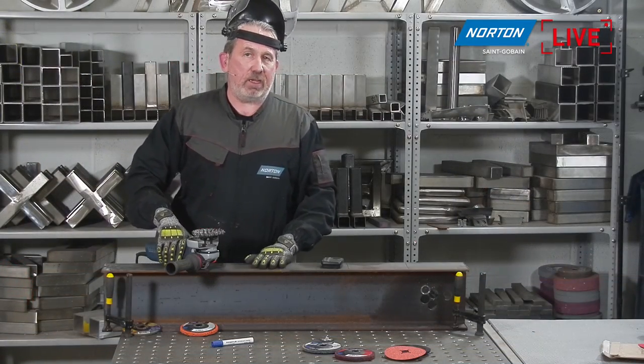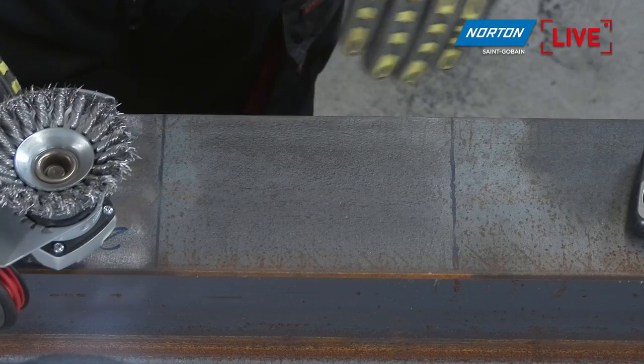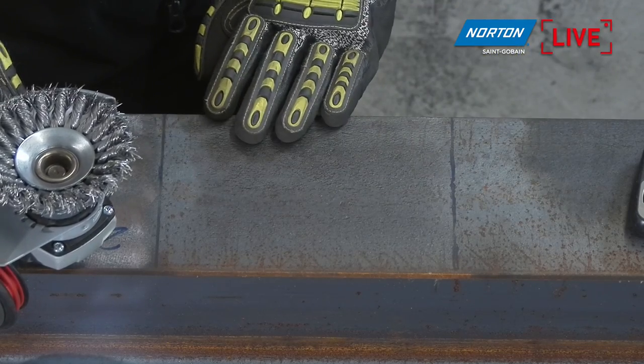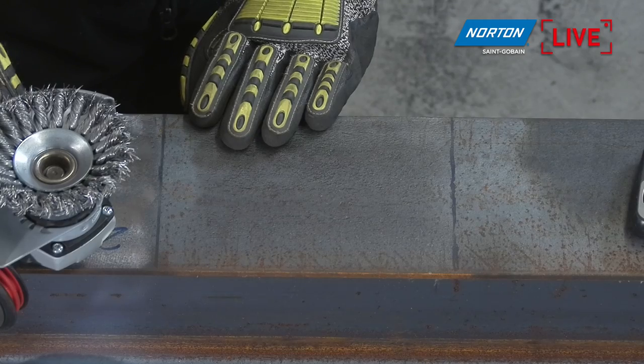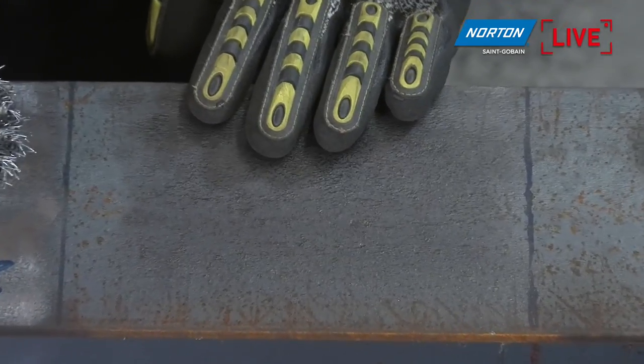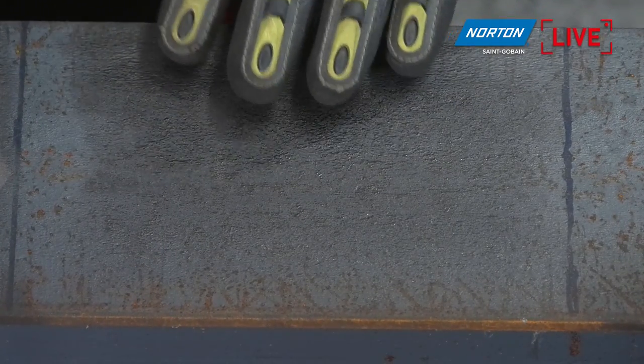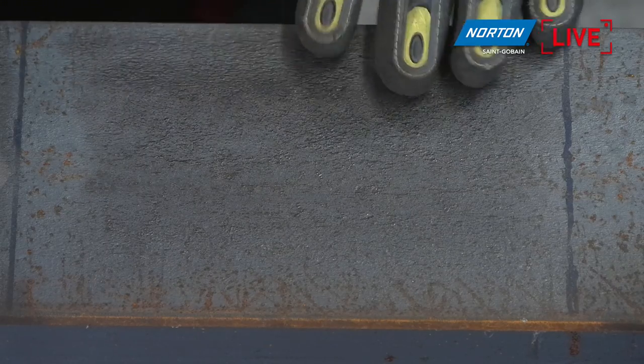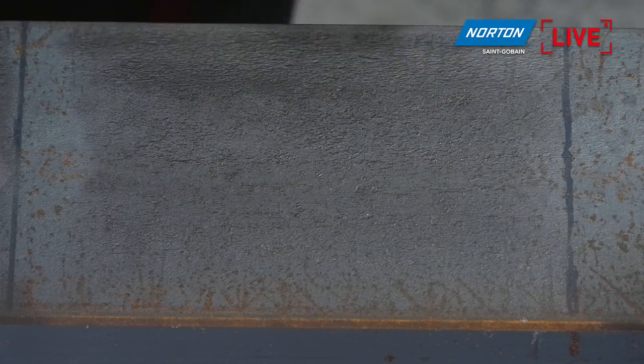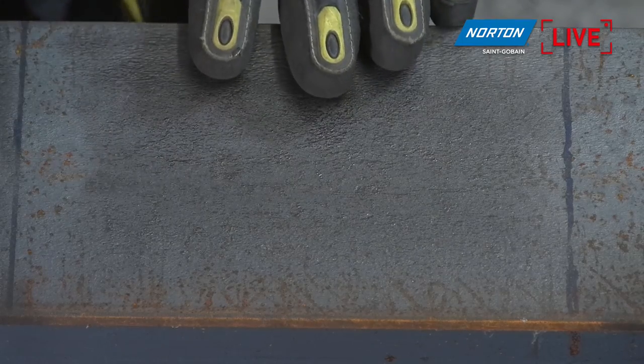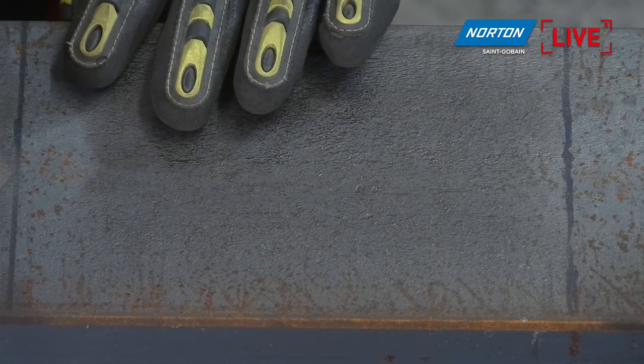Okay, slight issue with that product. I think if we take in the close-up on there, please, Martin, you'll see we've cleaned off some of the surface layer, but what the wire brush hasn't been able to do is break through the scale here. Because it's quite hard, this scale, it's kind of just polished up the surface of that scale, but it's not got through that to the underlying substrate.